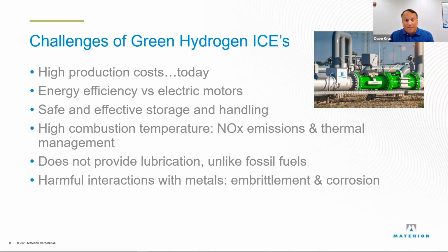Same will happen with hydrogen. The other thing that happens, as I mentioned, the efficient combustion, it's a high combustion temperature. So there is some NOx emissions that need to be controlled in the engine design as much as possible. And there's also thermal management issues. You're getting more heat. You got to have a way to either remove it or put it where you want it, keep it where you want it. So materials that can conduct very well and operate at high temperatures are important. Running a rich mixture in hydrogen isn't like running a rich mixture in a gas engine. It doesn't lubricate. And so you need low friction materials that work well in starved lubrication conditions.